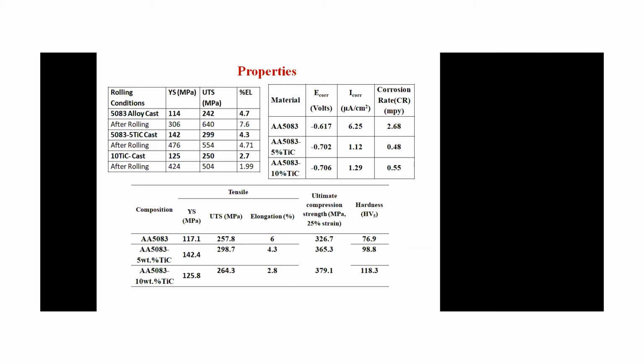So the simple alloy is there. After rolling, you get a more or less higher grain size, but after rolling the ceramic reinforcement composite, you get finer size, and the particles are also finer. So they act as a pinning for the dislocation. That means this gives you the Zener pinning or dispersion hardening strength. So that's why we have to use finer particles, and finer doesn't create any casting problem.